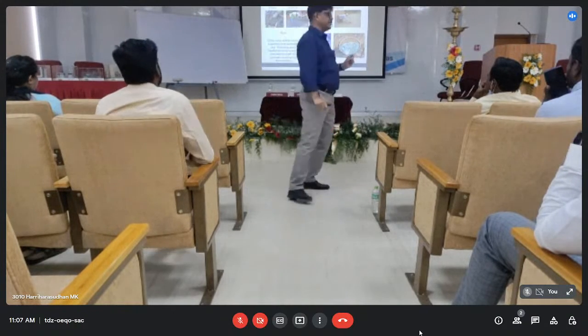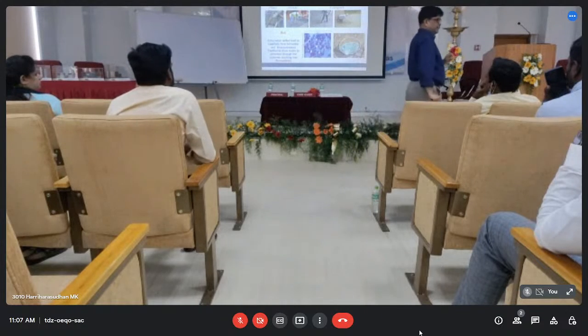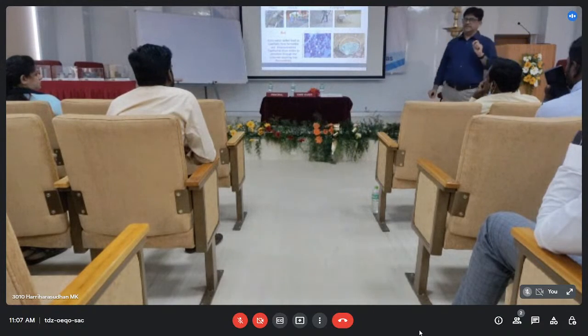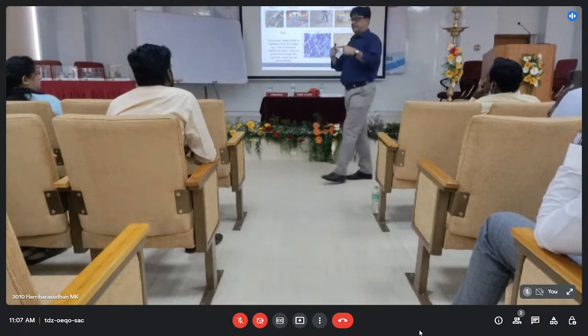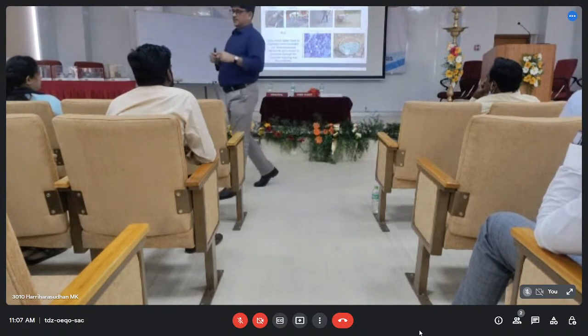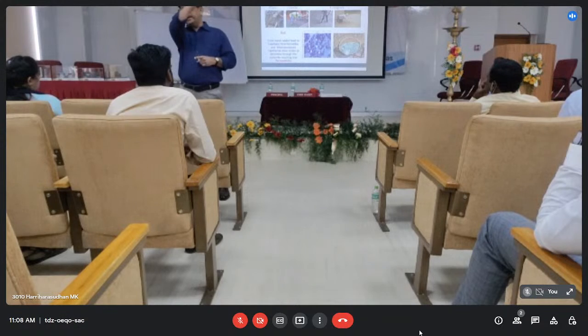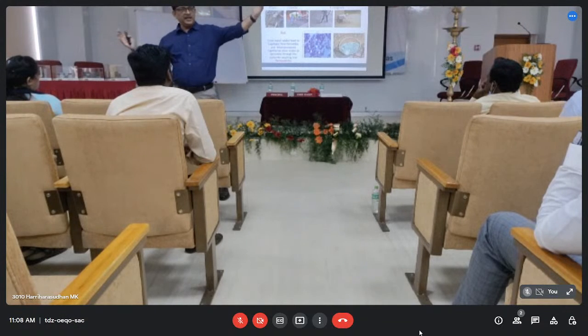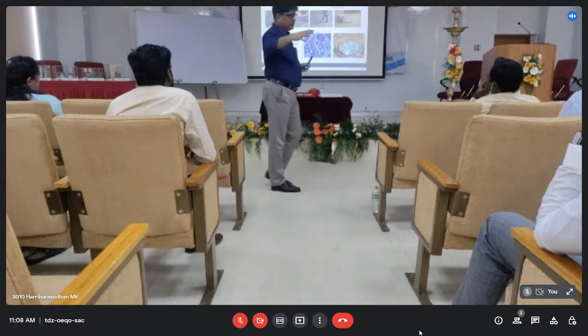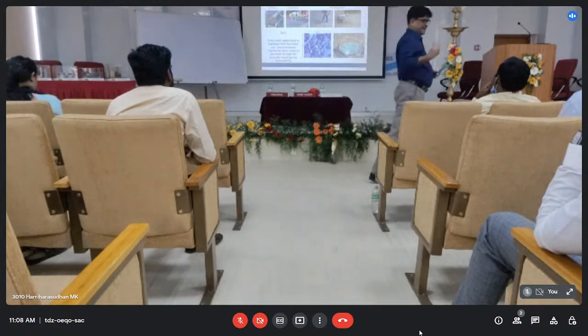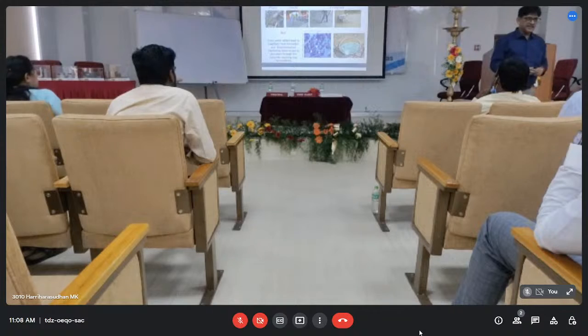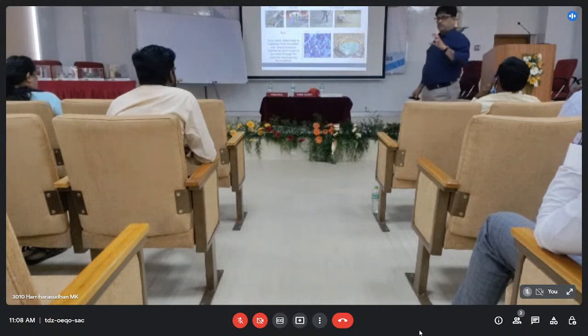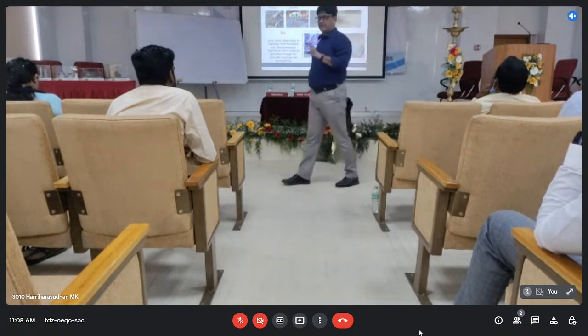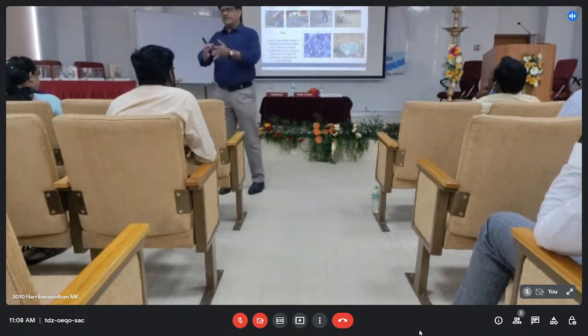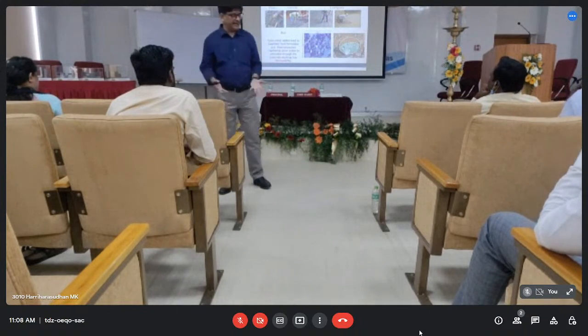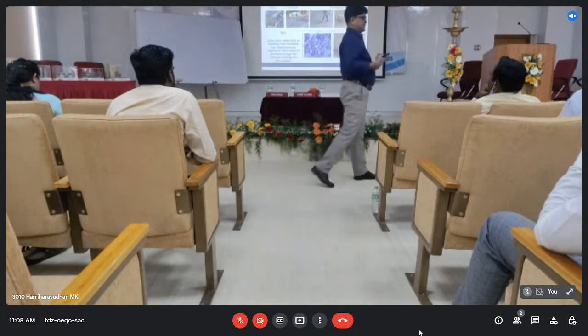Now again, capillary pores are not the problem. Capillary pores can be there. But if the capillaries are interconnected, the problem starts. When your capillaries get interconnected, you get a continuous flow of water from the surface into the concrete. And then you have leakage, seepage, dampness, all these things. So this is one of the most critical parts, which we try to overcome. We have admixtures, and we have a lot of things which we try to overcome with. We reduce the water as best as we can.